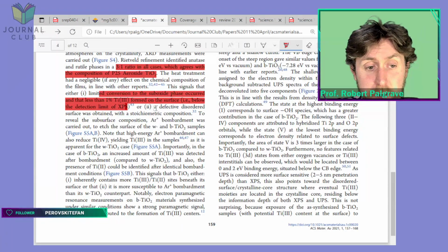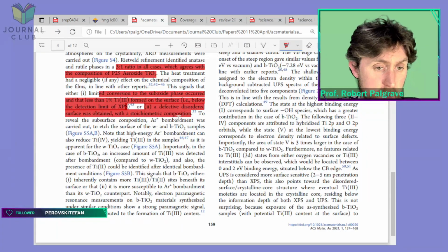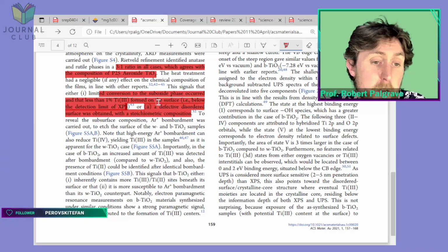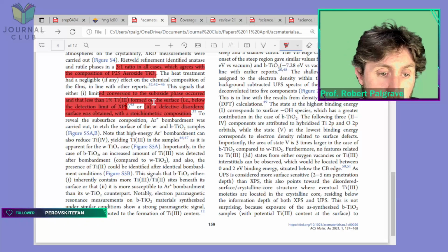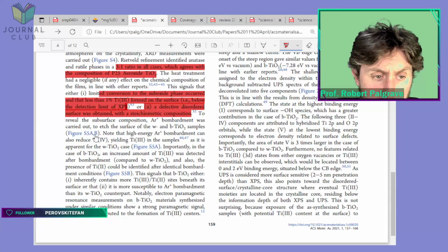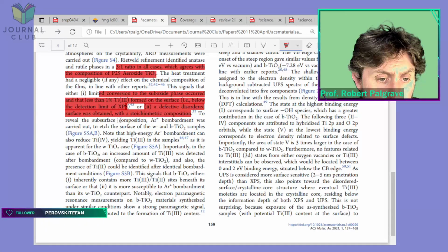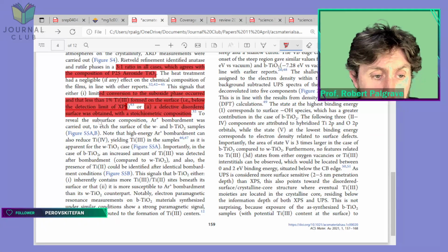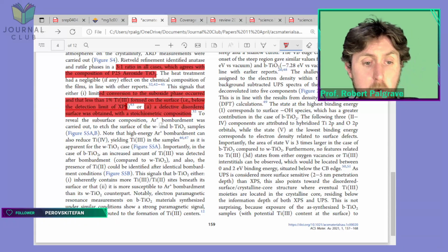Yeah, this is definitely not talking about the XRD. This is talking about the XPS. The XRD doesn't really tell you about the surface. It's a bulk technique. So I think maybe they just got these parts in the wrong order. To reveal the subsurface composition, argon bombardment was carried out to etch the surface of white and black TiO2 samples.